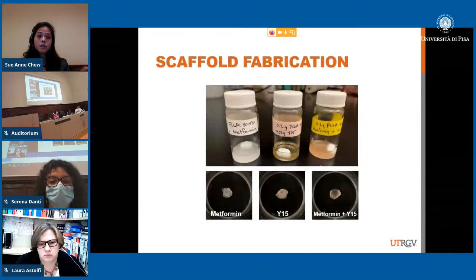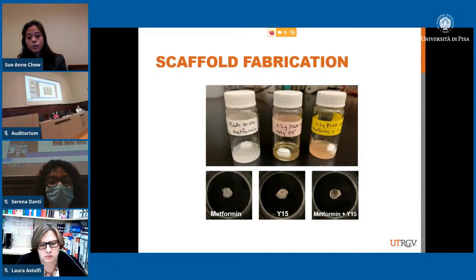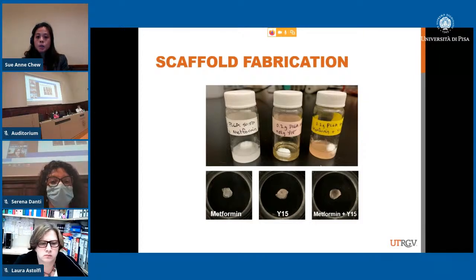So with this work, we wanted to see, let's try combining it with a biomaterial. Let's see if we can improve it, right? So we used that same model we had, the PLGA particles, the PLGA scaffolds that we make with the moldless technique. We made different solutions for them, just so that you can see how it's done here. And then we inject it into PBS and form those globular scaffolds.